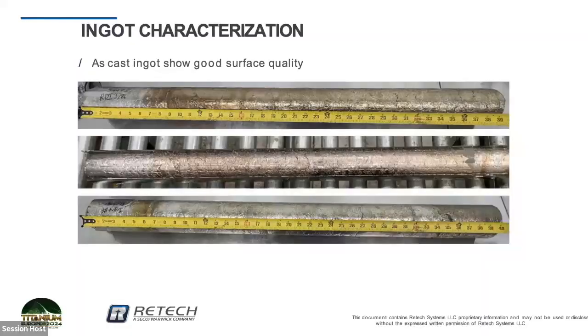The typical sizes of these ingots can be anywhere from 2-inch to 10-inch. And these are some examples of Ti-6-4 oversized powder that was consolidated to form ingots. You can see that the surface finish is fairly decent. And when we did the chemistry on these and the density of these ingots, they were very good, very close to what was the input powder.